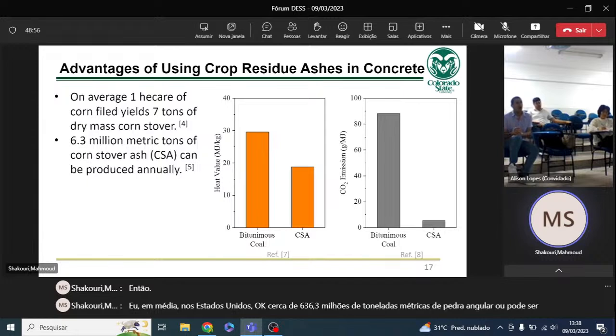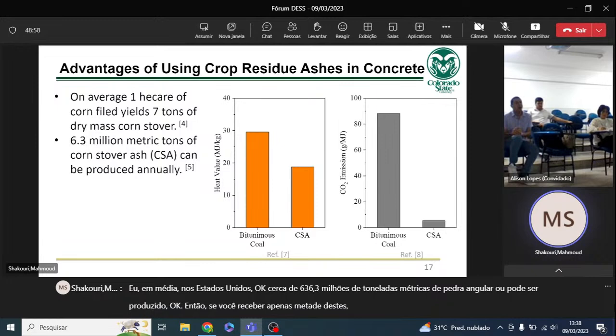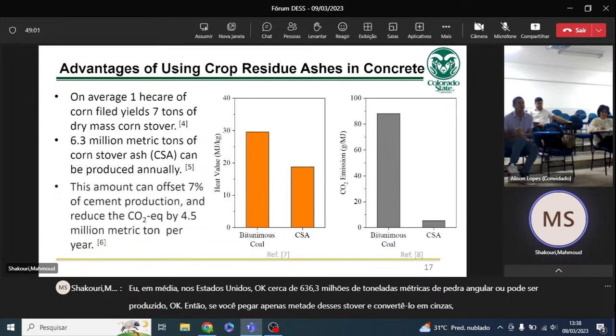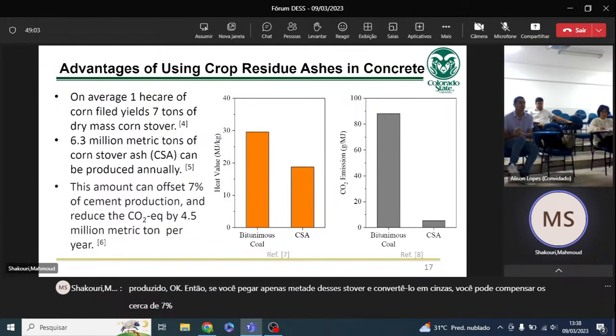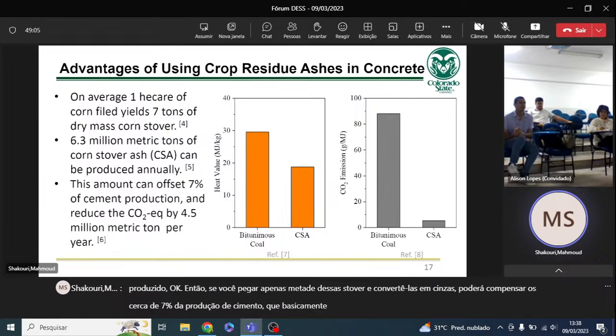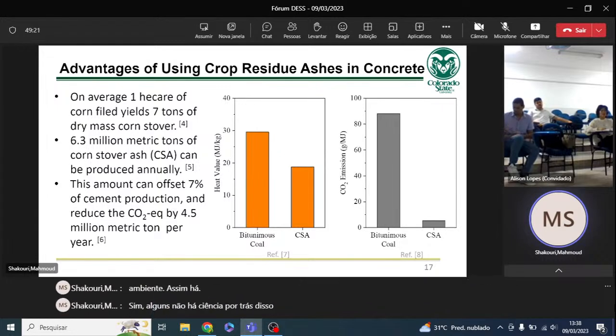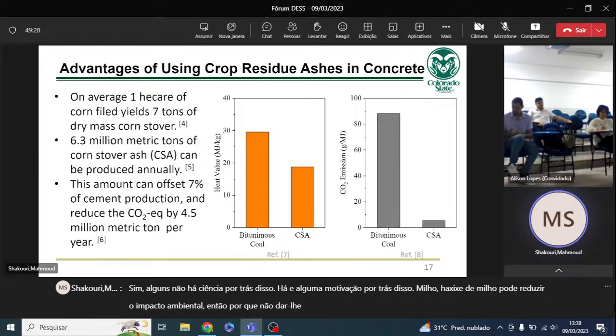Okay, so if you get only half of this stover and convert it to ash, you can offset about 7% of cement production, which basically is a huge value. You can reduce the CO2 emission by about 4.5 million metric tons per year. So that's a huge value if you want to change the environment. So there is some science behind it. There is some motivation behind it. Corn ash can reduce the environmental impact. So why not give it a try and see how it works?